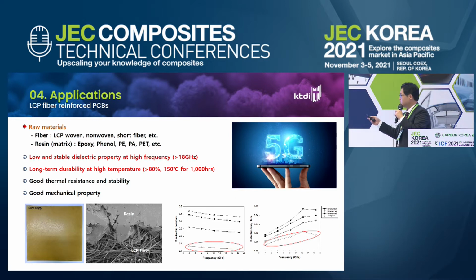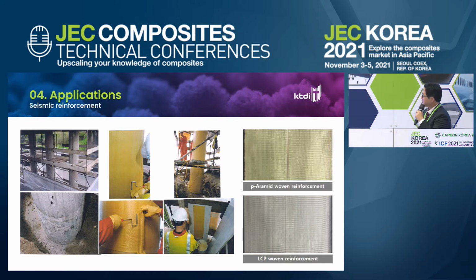And recently, we also applied for a patent for this one, which is using the LCP fiber to create a panel. And we did the measurement, and we could see that compared to the composite material, it was a very stable product in terms of dielectric property. Because the higher the frequency gets, the greater the loss rate could be, it's important that we have a stable dielectric property. We use several types of non-halogen resin and other types of resin. But when we use LCP, even if we use the average epoxy, we could still get a low and stable dielectric property. And that was a project that we've conducted. So we've applied for a patent for that one.